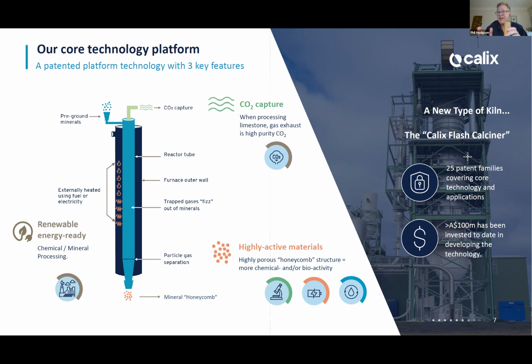The first key advantage is that, compared to, say, the cement and lime industries that use conventional kilns, where the furnace gases come in contact with the particles to heat them up, we keep it completely separate. The cement and lime industries' main input is limestone, and limestone by weight is nearly half CO2 trapped in the rock. When they heat that up, that CO2 comes out of the rock and basically just goes up their stack.